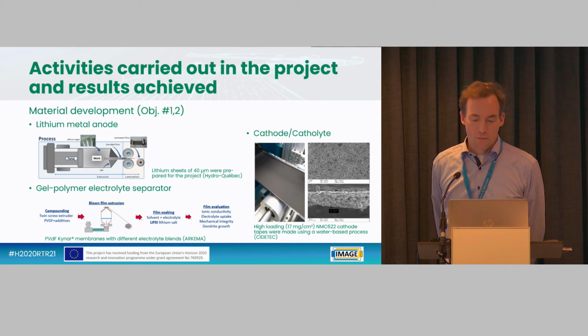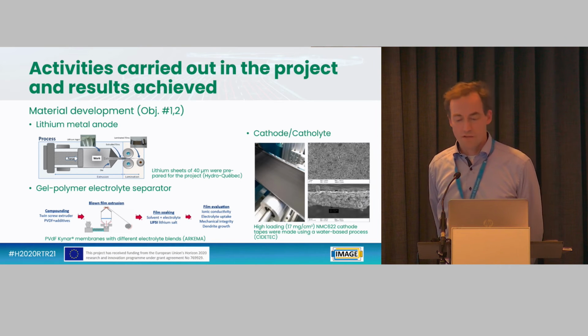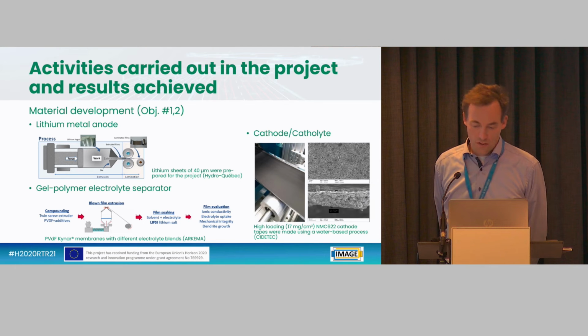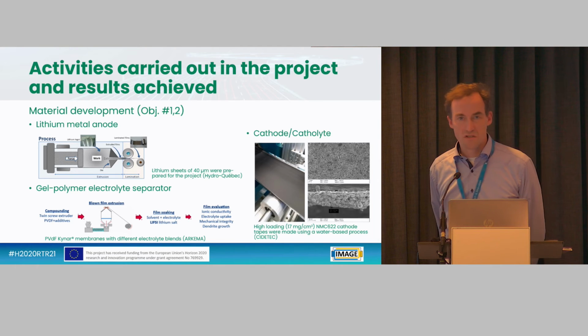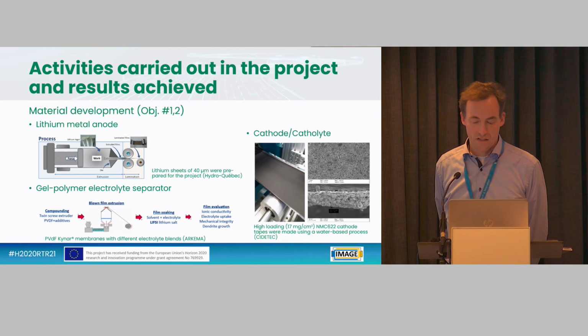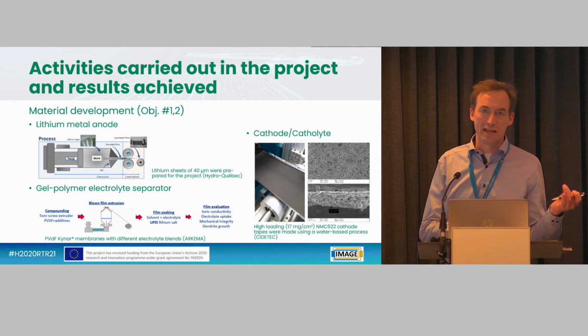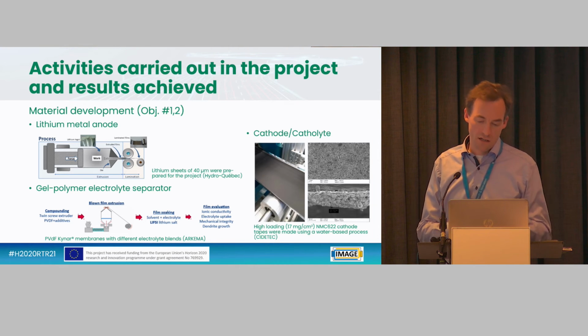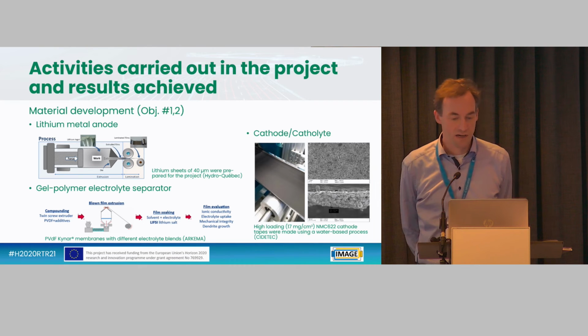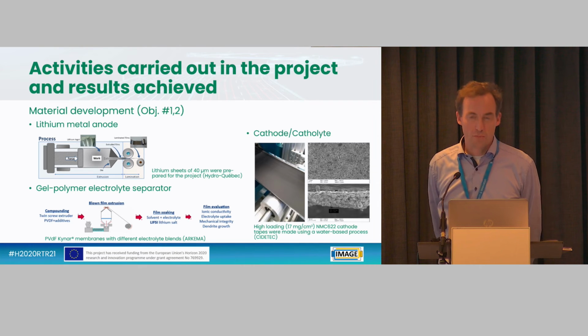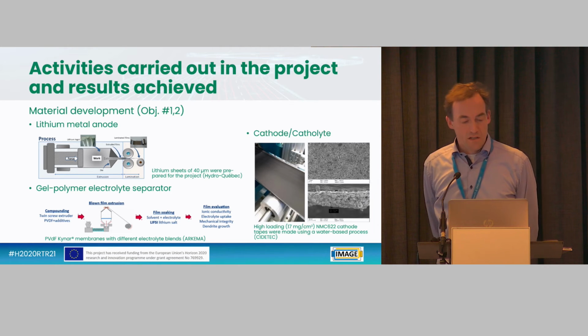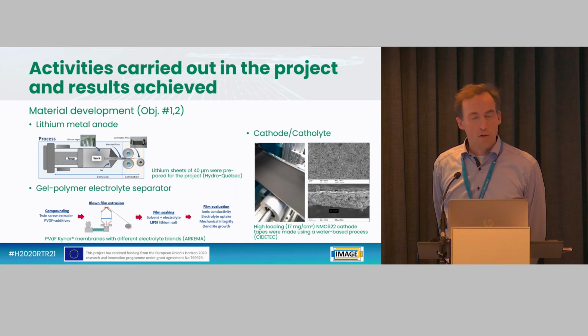First attempts were with normal NMC. If you take a normal NMC and do it in a water-based process, it does not work out. The active coating is rather brittle, and the adhesion to the aluminum current collector is very bad. So some modifications had to be done there, and also the manufacturing of the cathode tapes had to be optimized afterwards. And the third major component is the gel-polymer electrolyte.